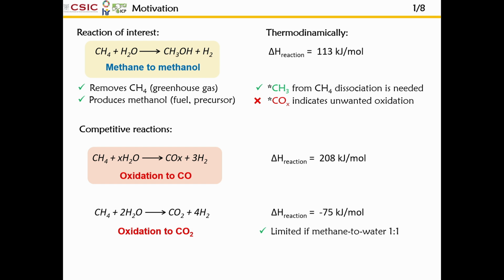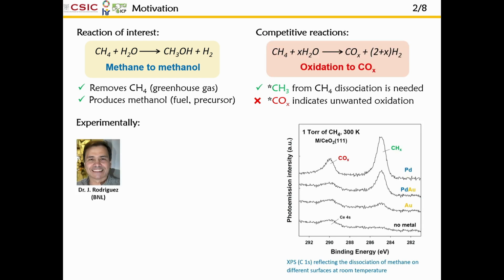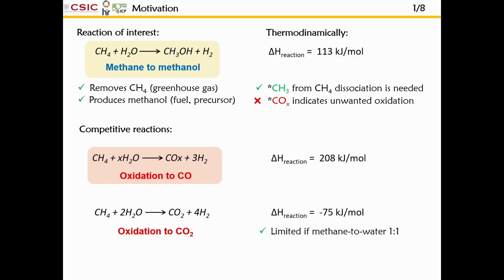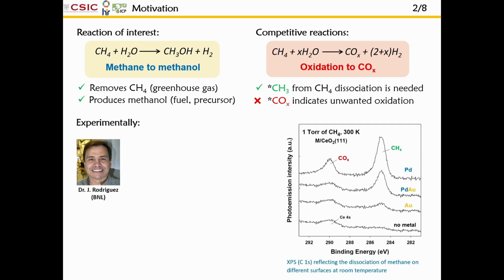But as usually happens, this reaction has competitive reactions. And so the idea is that methane is a very stable molecule, and once you find a catalyst that is able to break the first carbon-hydrogen bond, then the resulting CH3 species is not that stable and tends to overoxidize to CO or CO2. So you need to find a catalyst that is able to stop here at CH3.